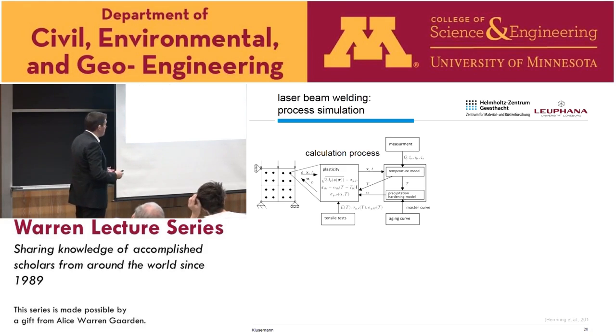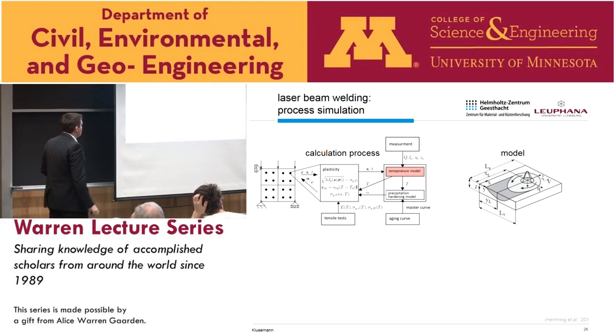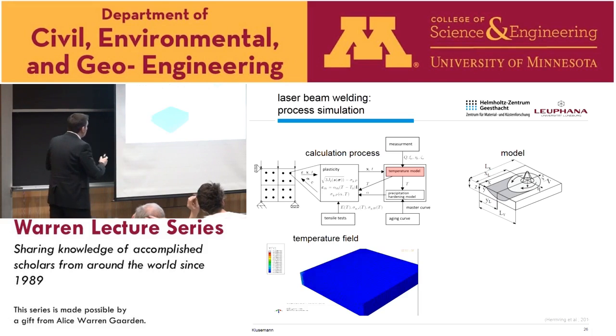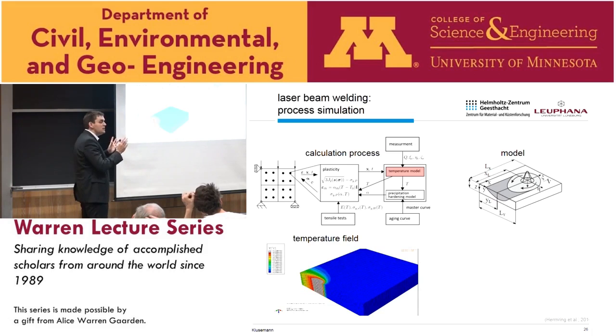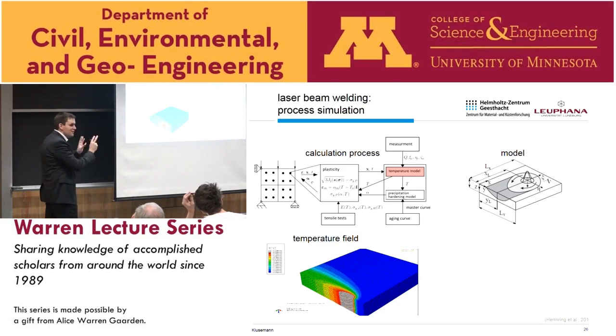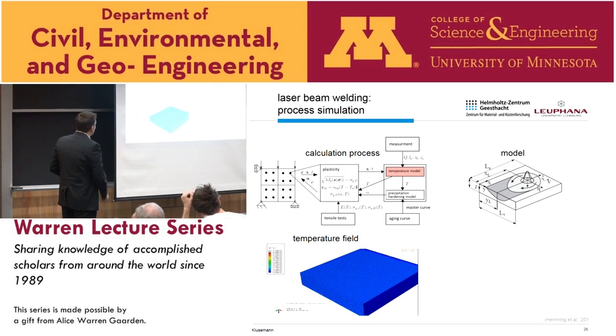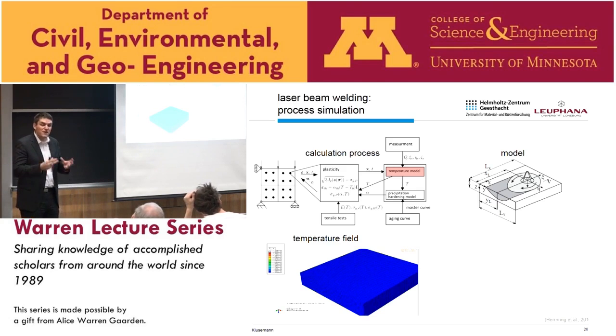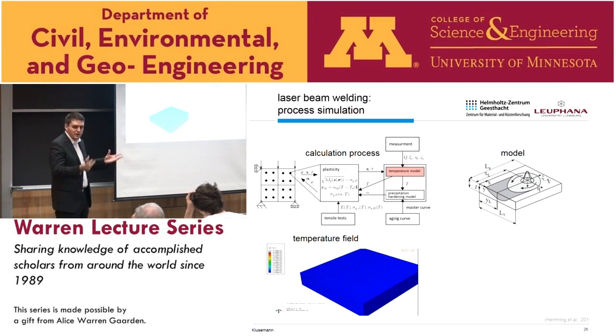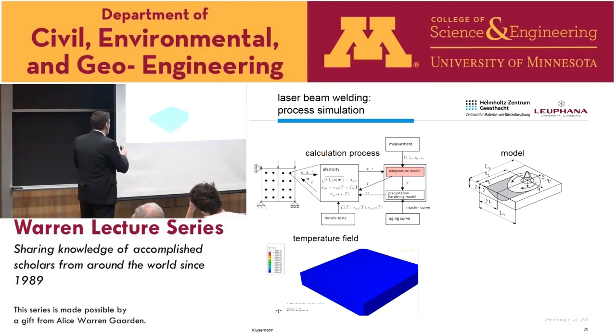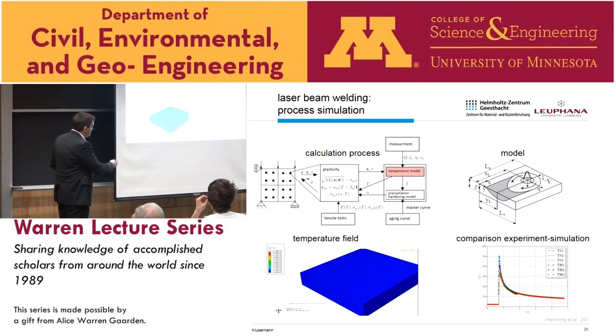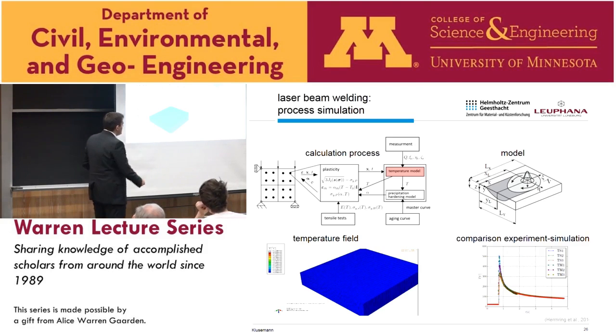The first step which we had to do, as you can imagine, this laser beam welding is quite fast, and we have extremely high temperature gradients. So one of the things we wanted to incorporate was a kind of temperature model. We used a very classical temperature distribution to model the laser heat input in our model, and we then obtained an analytical formulation based on Green's functions. I avoid the equations now, and could predict the temperature field directly for the simulation in a very fast way. So it costs in principle nothing, we can directly incorporate this into our finite element simulation.